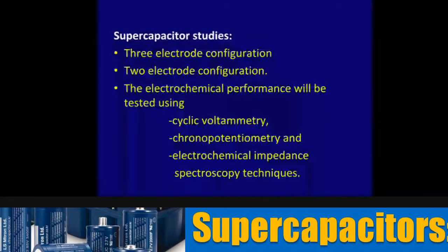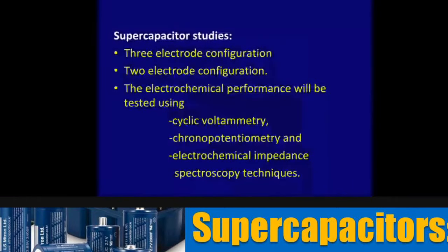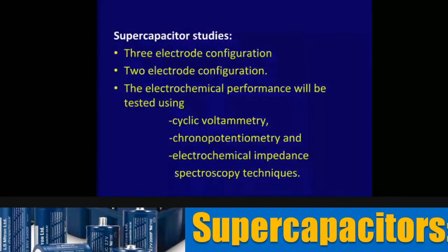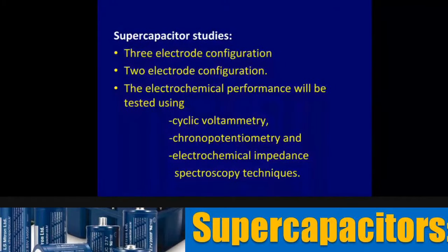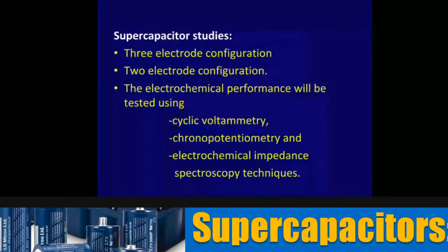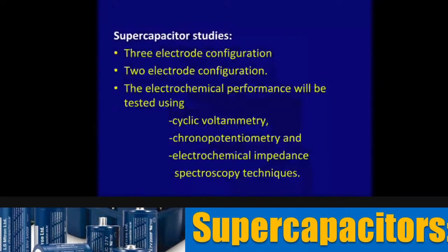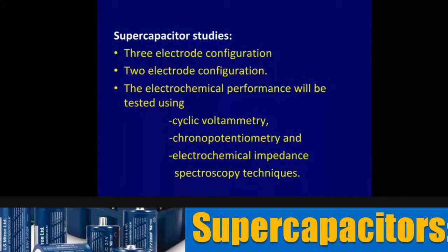The reason why we do all these things is to find out whether the ability of the device to accept and give out charges is good. This is measured in terms of what is known as a coulombic efficiency, where we try to see the amount of charges dumped in and the amount of charges taken out. But our knowledge normally tells us that if you want to study a capacitor, charge it and look at the potential buildup. And that's exactly what chronopotentiometry is about. Unlike the usual charging experiment that we do at the laboratory, what we do here is we try to use a constant current source. At a constant rate, the capacitor is charged and discharged at the same rate. And we look at how the voltage evolves with time. And that actually gives you why it is called chronopotentiometry. We try to look at the potential across the device as time evolves.